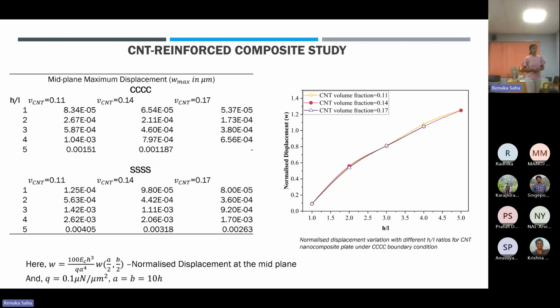Further, we have also done some parametric studies wherein we are varying the H by L ratio from 1 to 5 for different CNT volume fractions and for different boundary conditions. We can see that the slope for the normalized displacement reduces, showing that a higher thickness leads to results much closer to classical results, whereas for a thinner plate we see much more impact of the material length scale parameters. This has been captured here for different CNT volume fractions.